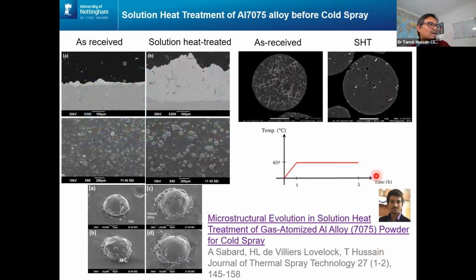Moving on, some of the other work we were doing was on aluminium alloy. So this one is an aluminium 7000 series, and that's an as received powder particle, and that's a solution heat treated one. One of the challenges of aluminium alloy, because these are precipitation hardenable alloys, when you repair it, you still have to do a heat treatment. And as soon as you do the heat treatment, you may lose the certification on that part.